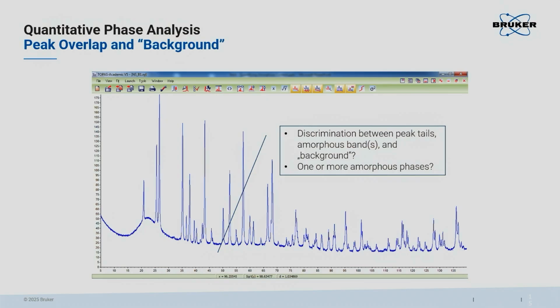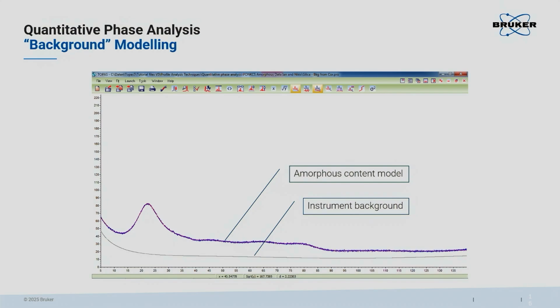So what we typically do is as crude as the powder diffractionists with the single crystals. We just subtract the background and ignore it, right? It is a point which is also becoming important for you, I believe, tomorrow. I do not know what Max is going to show in detail, but the subtraction or the determination of not simply background, but the capillary in your data, if you do PDF analysis, has the same background when it comes to determining between the capillary intensity and the actual sample intensity. So what I'm going to show you later today is a methodology which you can also use in the context of PDF analysis.